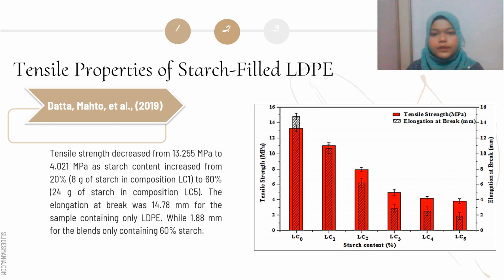According to Mato et al. 2019, to measure the effect of this on the mechanical properties of the produced film, different starch compositions were blended with LDPE. Tensile strength decreased from 13.255 MPa to 4.021 MPa as starch content increased from 20% to 60%, as shown in the figure. The non-uniformity created by the hydrophilic starch and hydrophobic LDPE results in low interfacial adhesion of the two polymers, resulting in low binding of the molecules, which is exacerbated as the starch content in the matrix increases.